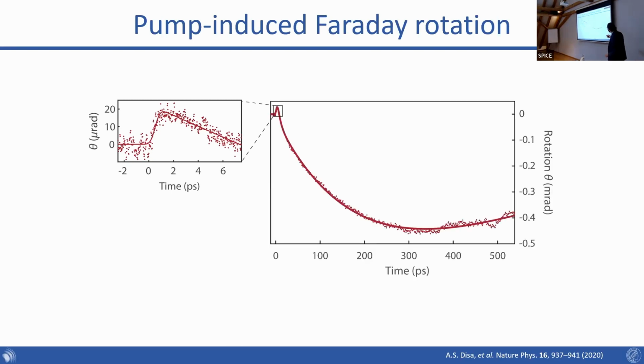What actually happens if you look on longer time scales is that the signal crosses through 0 and gets much, much, much bigger, and reaches a maximum after a few hundreds of picoseconds. And this is actually the magnetic signal that we're interested in. And here is just a coherent artifact corresponding with the excitation of these phonons. And you can verify this in a number of different ways.